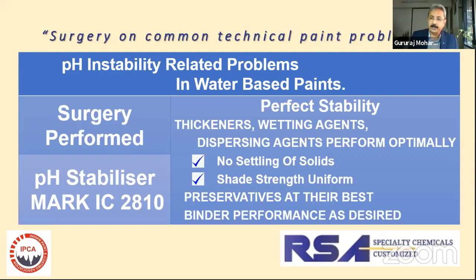One thing I would like to point out or stress upon is that addition of a pH stabilizer, especially in your water-based paint, has to be done at a later stage, after you have added your acrylic thickener or whatever thickener, activated it with liquor ammonia or ammonia-free activating agent. After that, when the whole process is done, then add a pH stabilizer. Otherwise, your pH stabilizer can be used for activating your thickeners, and then it will not be there in the system to work for your stability over a period of time.